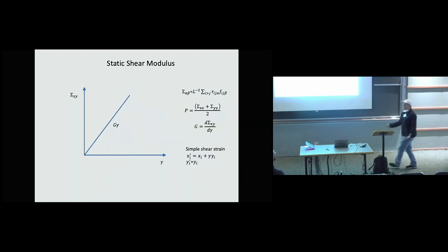And that's relevant for fluid-driven granular beds because you're interested in what's the shear stress that will induce erosion or induce grain motion. And so I'm interested in the strength of these granular beds. If you have this linear system, the shear stress will grow linearly with the simple shear strain, and then the shear modulus will be the coefficient in front of that increase.